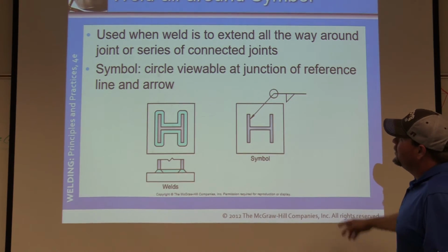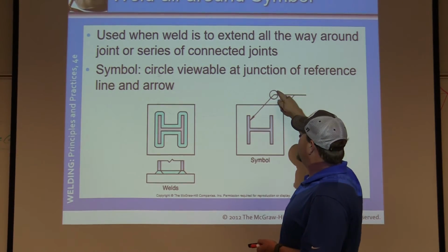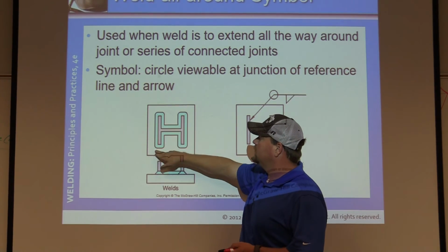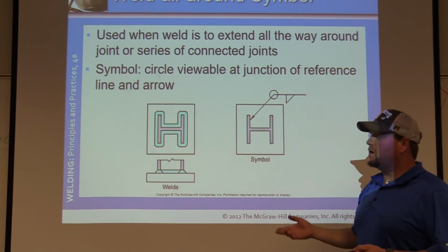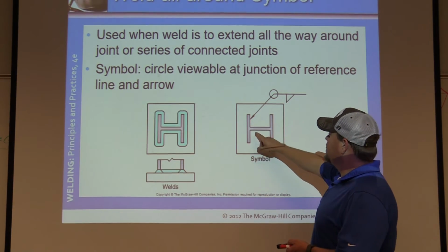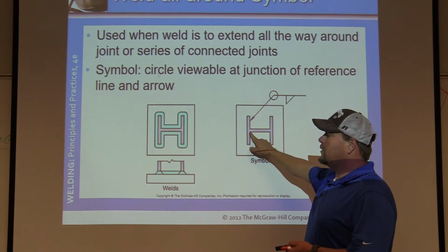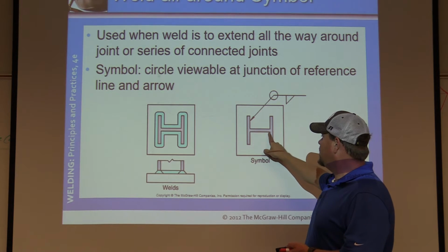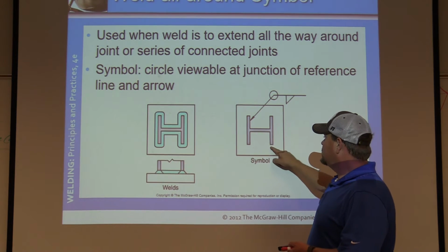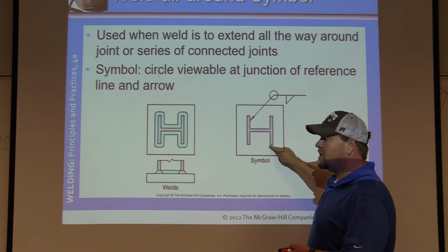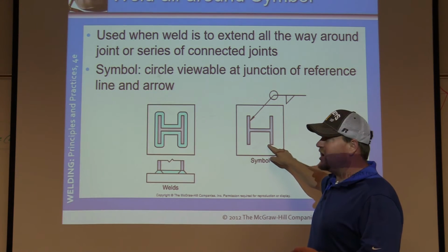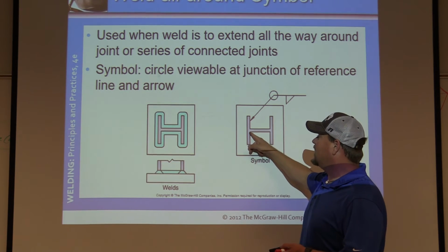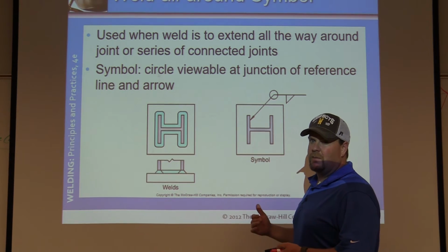Okay, fillet weld doesn't give us the size. Weld all the way around it. So we weld around the entire thing. Something that's really important to know, welding-wise, is you never start and stop in the corners. You always want to start and stop, go from here, around, stop here. Try to wrap around your corners. On an outside corner like this, you can start and stop here because there's easy access. But you never want to stop on the inside of the corner because you're taking a chance of getting slag trapped in that corner and not being able to get it back out, okay?